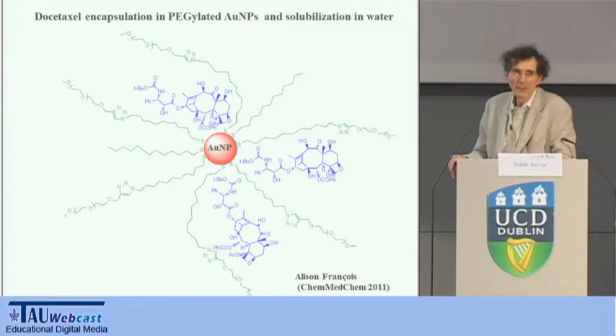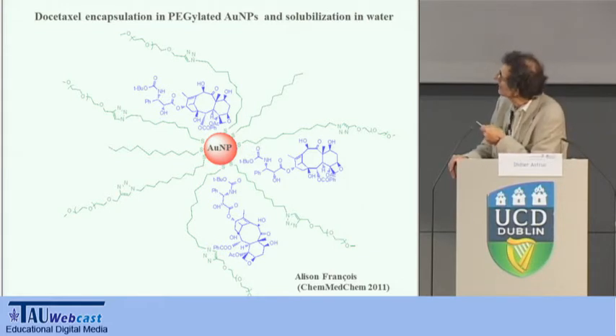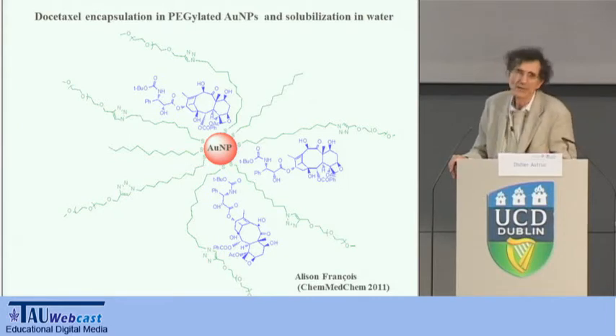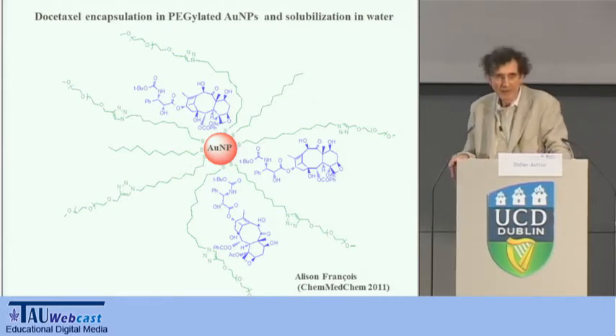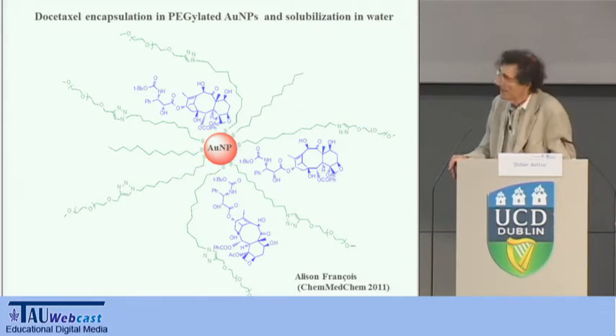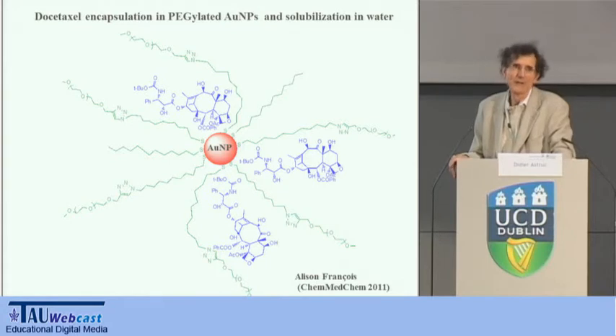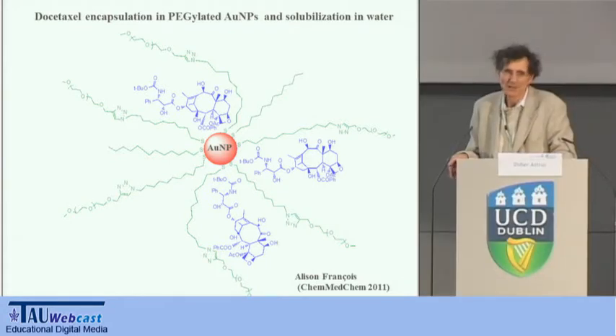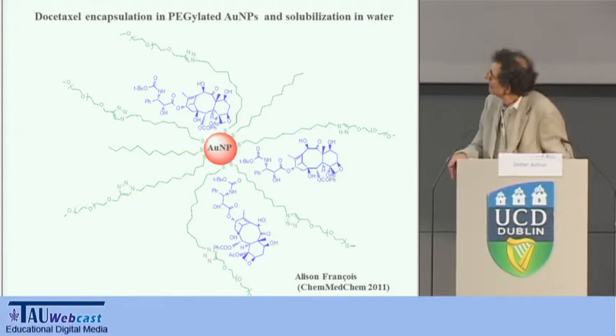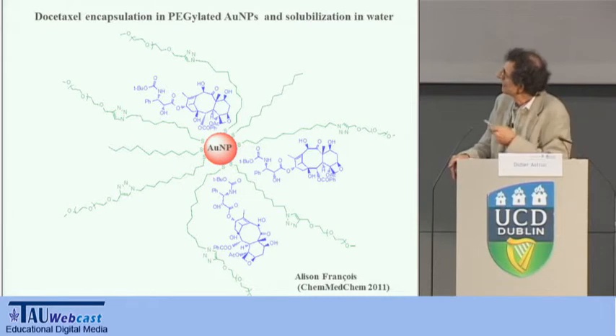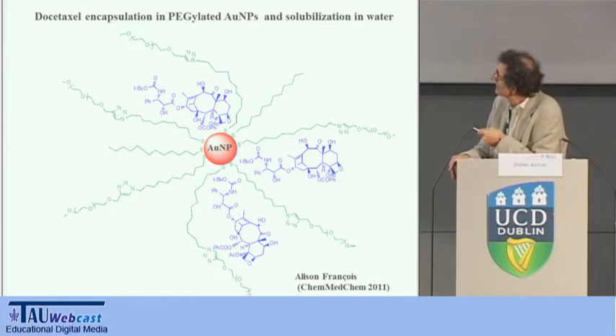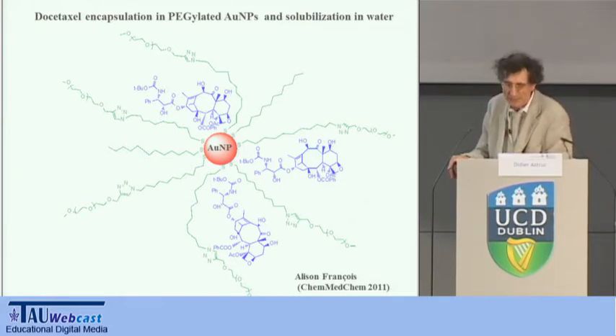And we have been using this gold nanoparticle to encapsulate an anti-cancer drug, a taxane, docetaxel, which is the most important anti-cancer drug so far, which is in use, which is commercialized. But the big problem is that it is not soluble in water, and you need to inject it into patients in aqueous solution. So the way to overcome this problem is to encapsulate the drug into a material that is water soluble. If you decorate the nanoparticle with a water-soluble periphery, polyethylene glycol, then it becomes soluble in water. And then you can use these nanosystems in nanomedicine eventually.